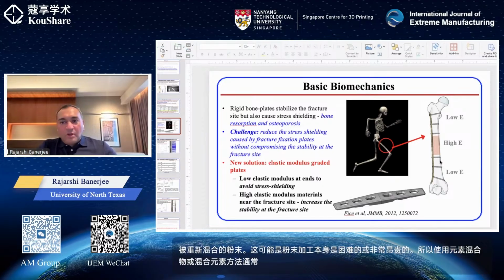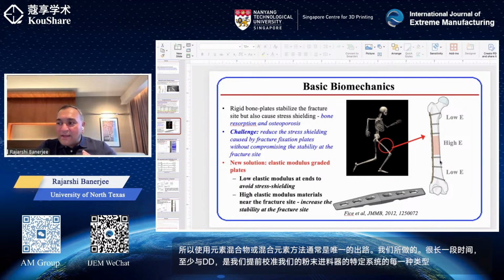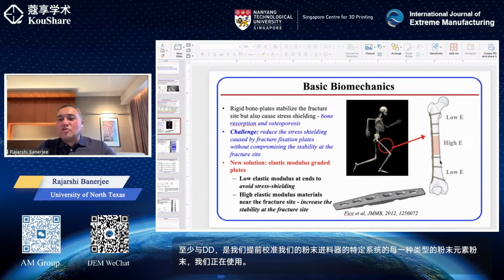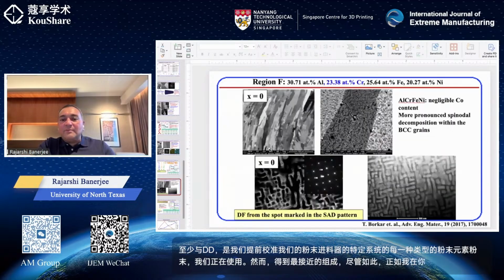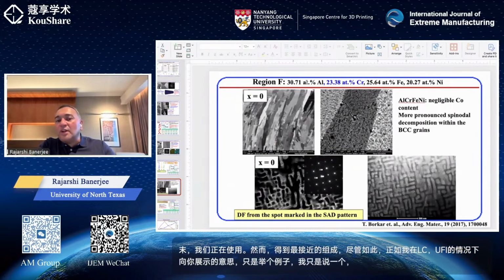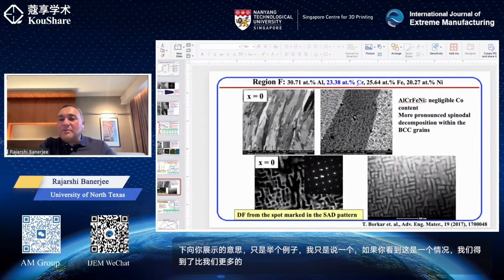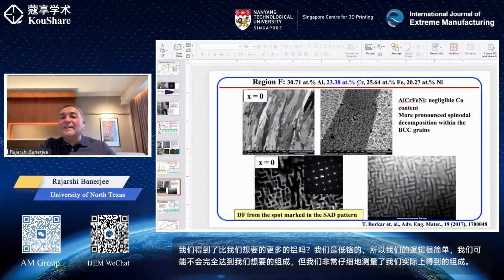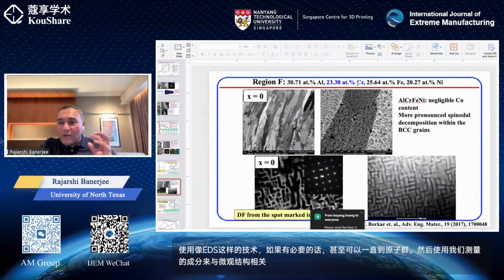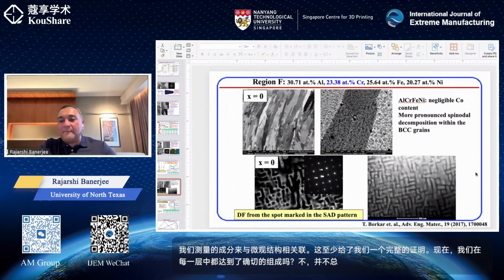What we have done over a long period of time, at least with DED, is that we calibrate our powder feeders for the specific system in advance for each type of elemental powder we're using, and get to the closest composition. However, despite that, as I showed you in the case of the AlCrFeNi, just to give an example, this is a case where we had more aluminum than we wanted. We had lower chromium. So our logic is simple. We may not exactly hit the composition we intended, but we measure the composition that we actually got very carefully with techniques like EDS and even all the way up to atom probe if necessary. And then we use that measured composition to correlate with the microstructure. So that gives us at least a foolproof correlation. Now, are we achieving exactly the composition in every single layer? No, not always. But within, I would say, a few percent, you can definitely do it, if you carefully do it.